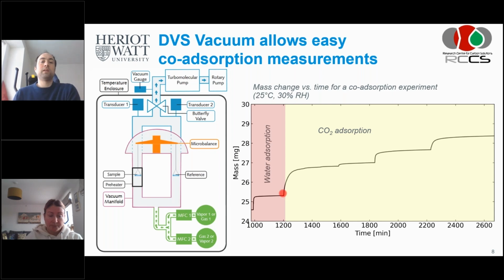So that means that the gases or the adsorbates aren't flowed over the material continuously, but they're pulsed into the system until a certain set point partial pressure is reached. And then once we have that baseline, so we have the water saturated sorbent sample, then we do a couple of steps of CO2 injection.